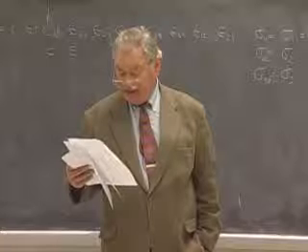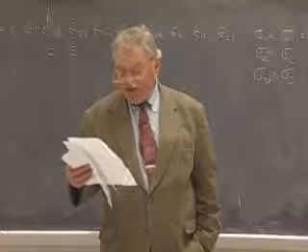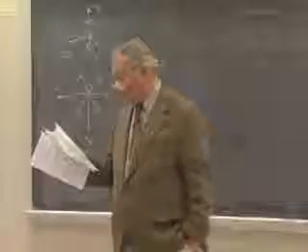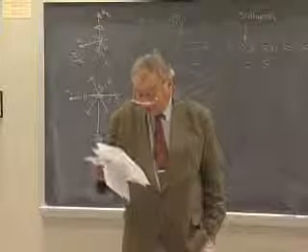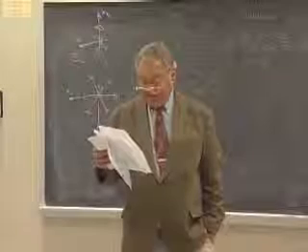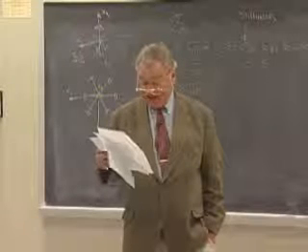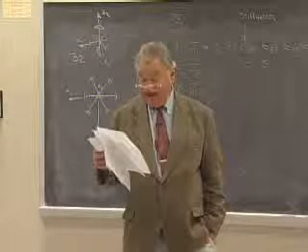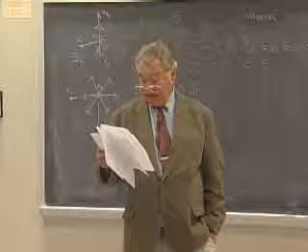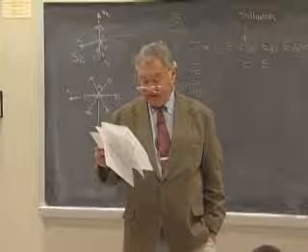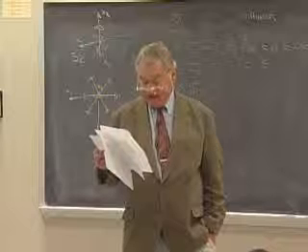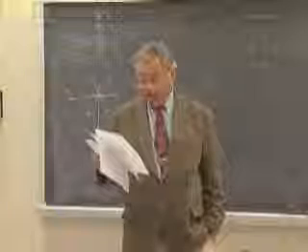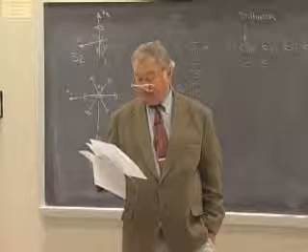Two things down here of interest. I said that cubic crystals are not isotropic. What would have to be the case if the material were to be isotropic? Well, it turns out that if you do this for the compliances S, if 1/2 of S44 is equal to S11 minus S12, then the material is elastically isotropic. If you do this in terms of stiffnesses, the C's, then 2C44 is equal to C11 minus C12 if the material is going to be isotropic.